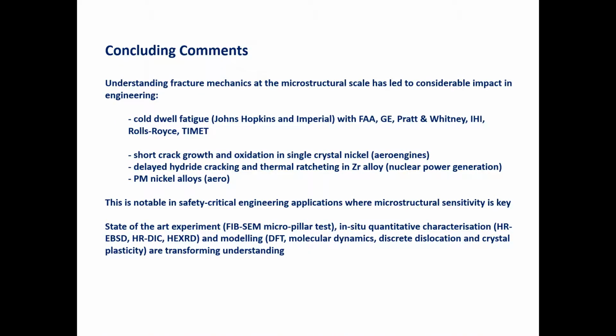So just a few concluding comments. We've hypothesized that stored energy density may be the mechanistic driver of microstructure-sensitive nucleation and fatigue crack growth, short crack growth, and we've tested that against a range of examples, both laboratory and in models. The sorts of approaches are likely to be relevant mostly to safety critical components, where design to ensure safety, of course, is crucial, but unlikely, therefore, to be relevant to all conventional engineering structural integrity, where detailed knowledge of microstructural